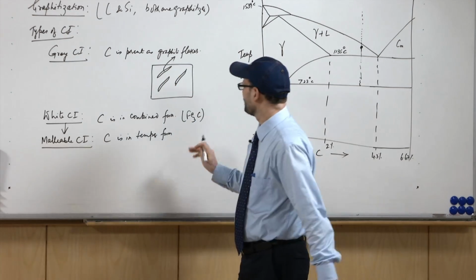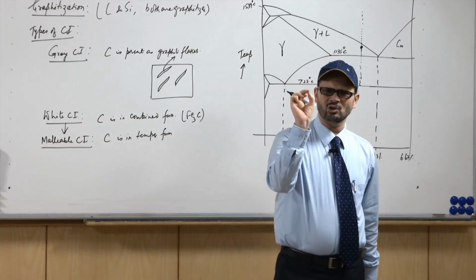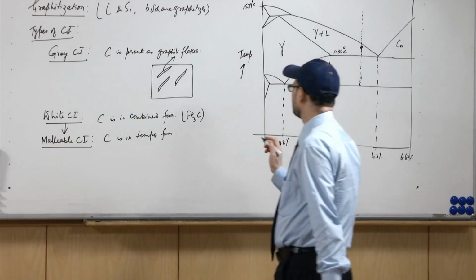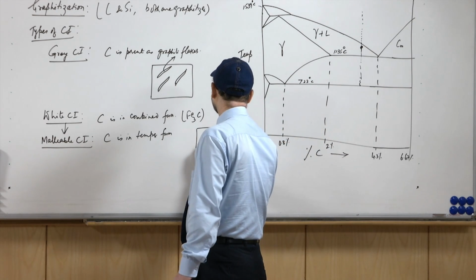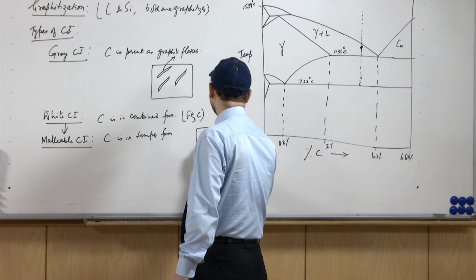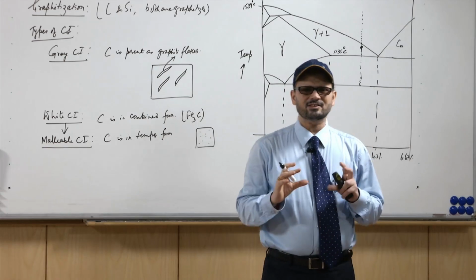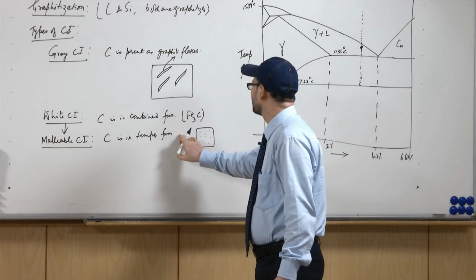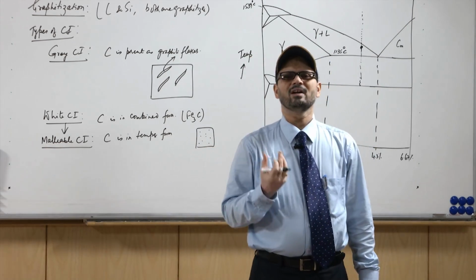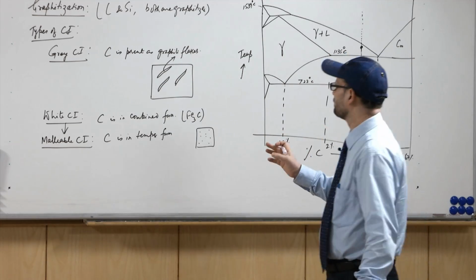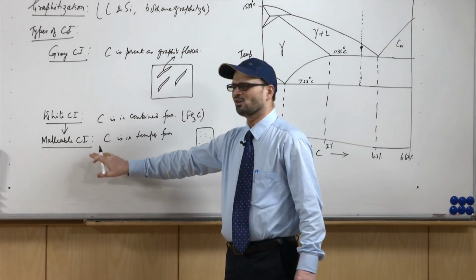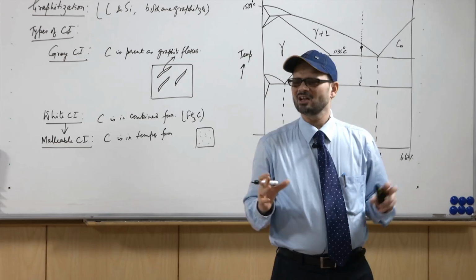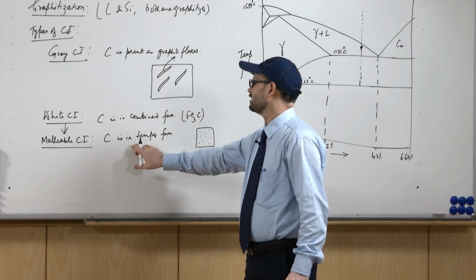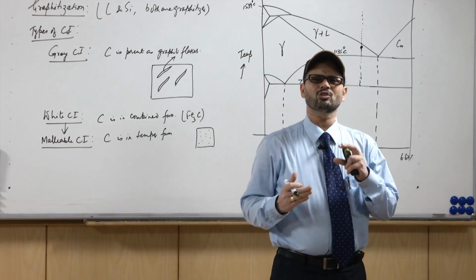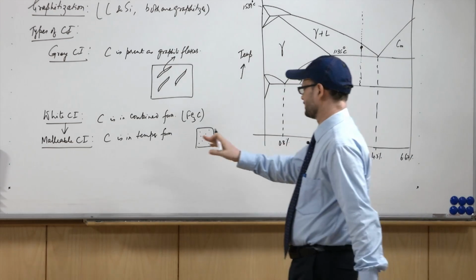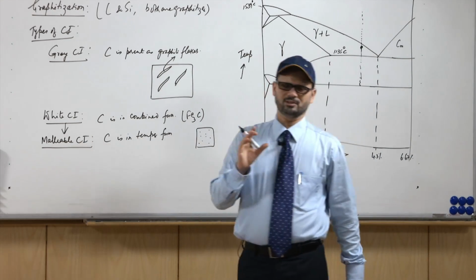So, temper or free form, this carbon is in small nodules. In that case you have smaller nodule-type structures of free carbon present, and it basically gives a large amount of ductility and malleability to the component. So, this malleable cast iron, although the heat treatment cycle is quite long, is used for many automobile components where you need the property of malleability and ductility.